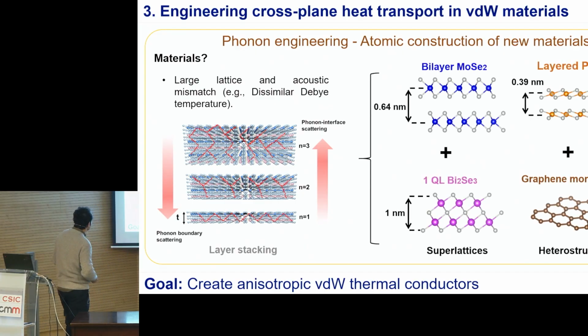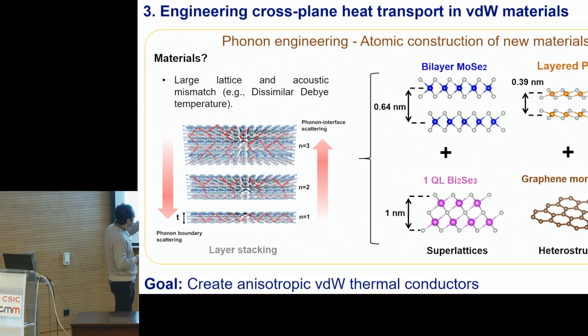So which are the materials to do this? We need to select materials with large mismatch in the acoustic properties, that have a very different Debye temperature ratio and large lattice mismatch. So what we did is to create this kind of superlattices with molybdenum diselenide and bismuth selenide. These materials have very large lattice mismatch.